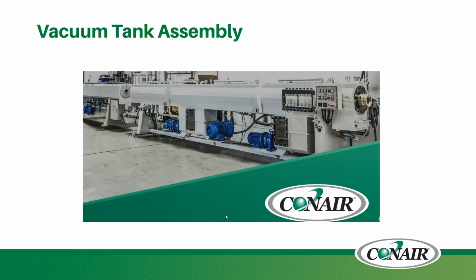And then, of course, you've got the vacuum tank itself. You can see the brass ring on the far right where it enters into the vacuum tank, and then more or less vacuum is applied to precisely control the vacuum applied to the product to get your OD and ID and subsequently wall thickness correct. And then from there, it goes into subsequent cooling tanks. There could be one additional cooling tank. There might be 3 or 4. There could even be more, depending on the size of the pipe and the amount of cooling required to have it be a solid product by the time it's introduced into the puller and pulled off for shipment.